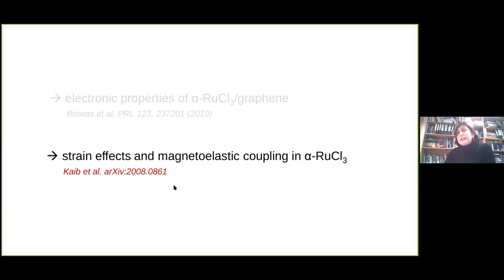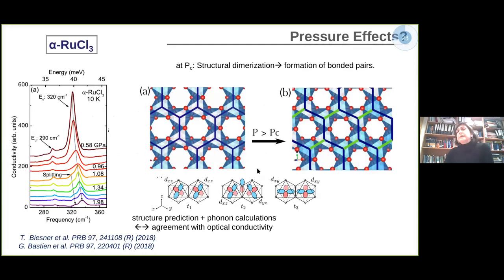So, of course, you can apply strain in your material either by constructing a heterostructure, as we did here, but also the simplest way of straining your material is first to think about hydrostatic pressure. But the problem with hydrostatic pressure, and these are experiments that have been done some years ago, and we also did simulations from ab initio, is that if you apply hydrostatic pressure, you basically favor precisely this type of hybridizations.